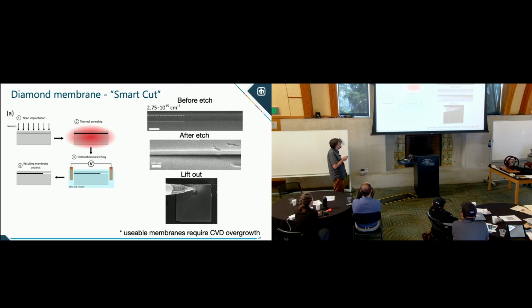And so here's an example of us doing it at Sandia. Here's a SEM image before, where you have darker contrast in this area, electrochemically etch it away, and you can see this, and you can lift out and put it on other places. Now, the reason that I'm not manufacturing this myself is because there's enough damage on that surface layer that the ideal way to do this is to smart cut and then do CVD overgrowth on top of that. And so we will do the smart cut part and then send out those diamonds to our collaborators for them to do overgrowth and make photonic devices on it.